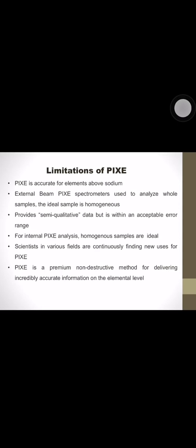If the sample is not homogeneous, it is best practice to test multiple sessions and take the average of the quantitative results. This provides semi-qualitative data but is within acceptable error range. For internal PIXE analysis, homogeneous samples are also ideal as x-rays are emitted from only the top few microns and thus non-homogeneous samples may produce inaccurate readings.